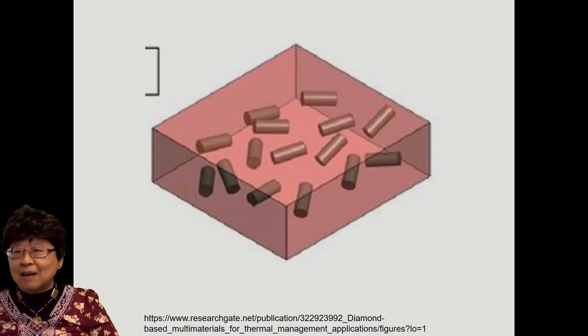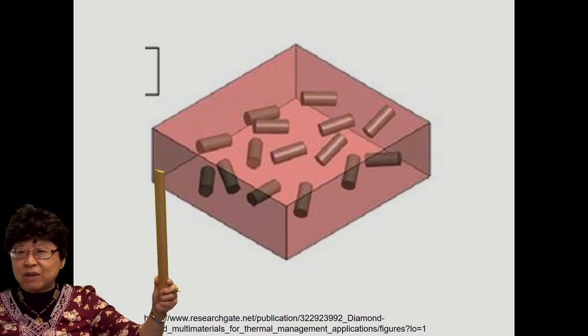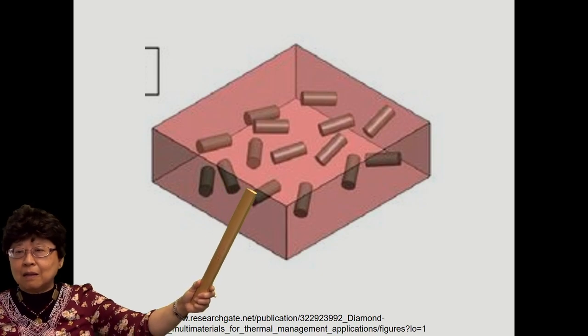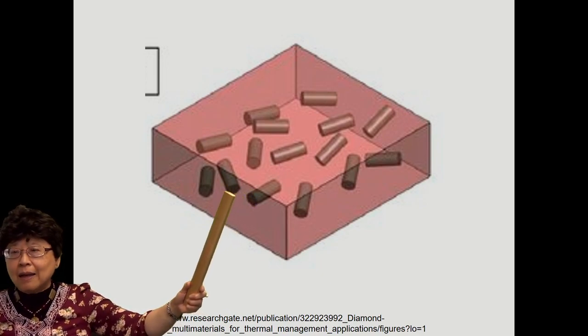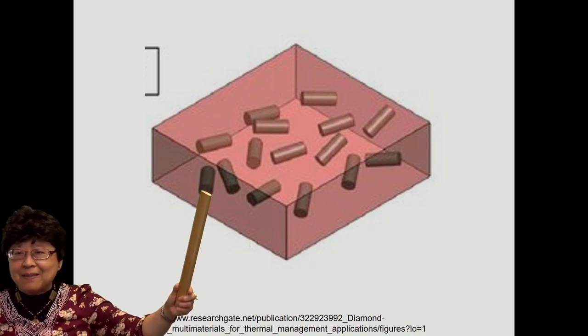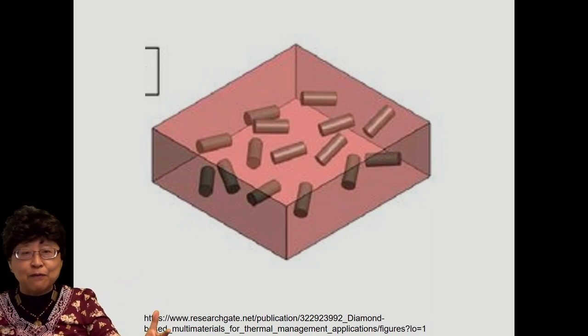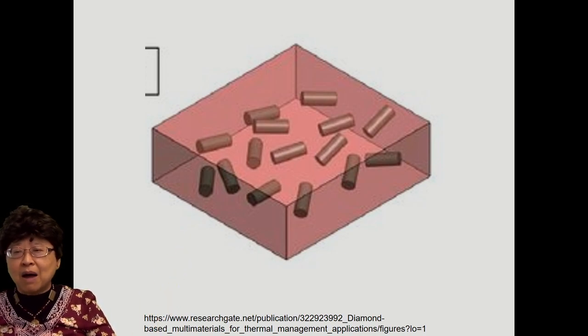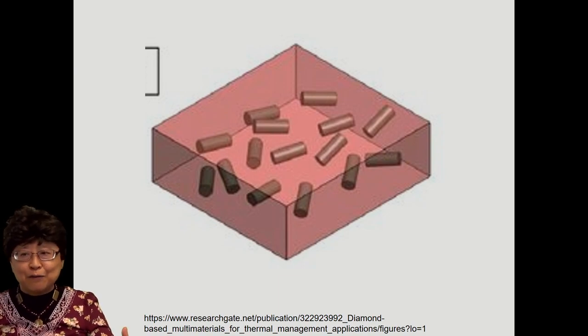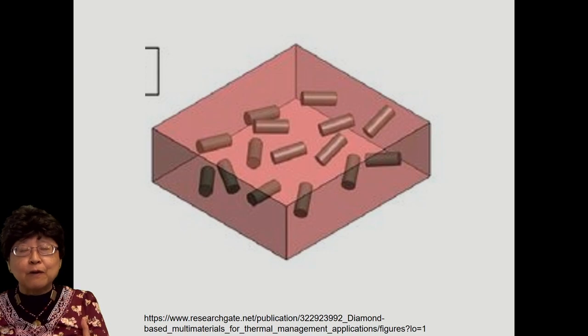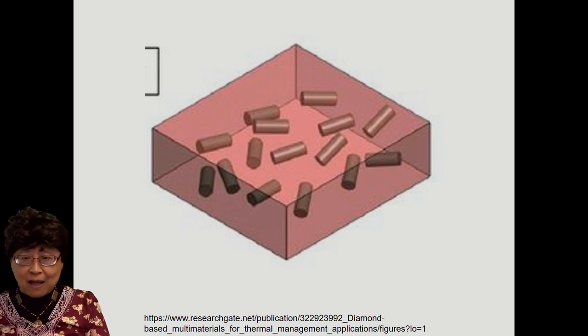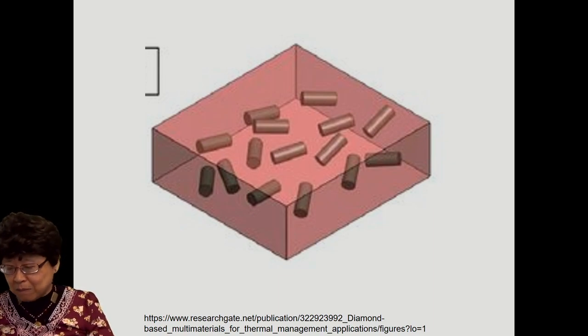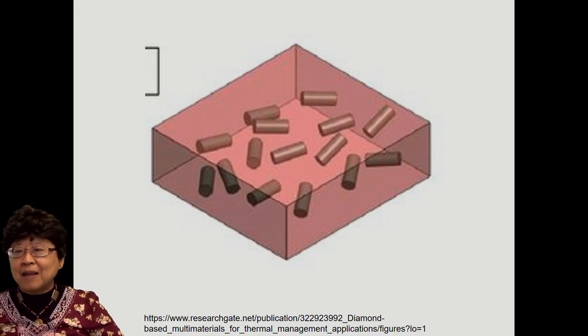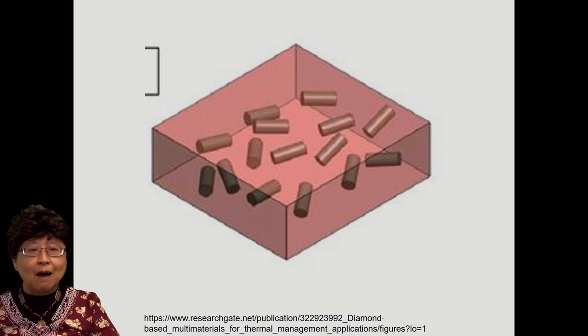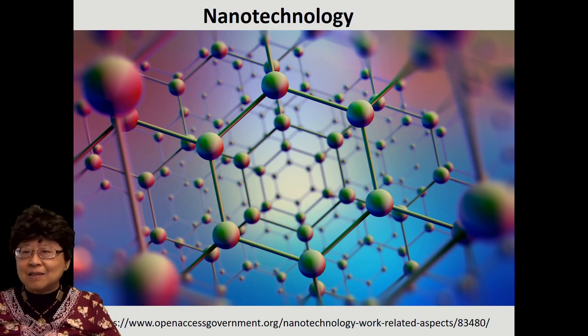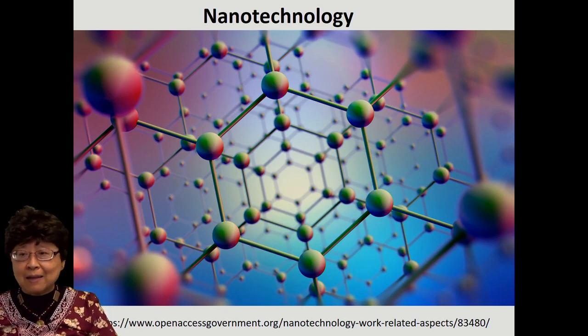Okay? So if you have a material in the form of a composite, the matrix is not able to shield, but you put some fillers in there, and the fillers are able to shield because they are conductive. And if each fiber here is big and fat, then the inside of each fiber is wasted, just sitting there, not feeling the radiation. So overall, the composite would not be very effective for shielding because you're wasting most of each fiber present. However, if each fiber has a very small diameter, then the whole of that fiber volume can be utilized in shielding, and that would make the overall composite much better for shielding. And nowadays we have nanotechnology, so nanofibers are available, and so this is an area where nanotechnology excels, that's for shielding.